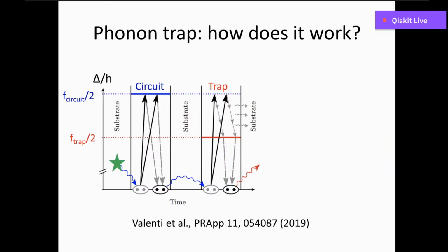This phonon can again travel through the substrate and break a Cooper pair in the trap, again creating quasiparticles. However, here, the quasiparticles will need to lose the excess energy before recombining. When they do recombine, the emitted phonon will be able to travel through the substrate, and it will also be able to reach the circuit again, but it will now lack the necessary energy to break Cooper pairs in the circuit.